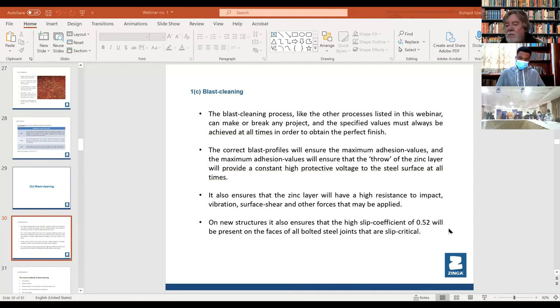And that remains constant. We did a pull-off check a couple of years ago in Norway, and the bridge was 30 years coated with Zinga, and the pull-off value was still 11.3 megapascal. So the blast cleaning done originally 30 years ago was very good. So this is a fantastic reference. Also, when you have the correct profiles, 50 to 70, or even a little bit deeper for marine work, if you have the zinc that goes into a deep profile, if you have any impact on the zinc, it's actually pushing it inside the profile. It'll never crack or split.